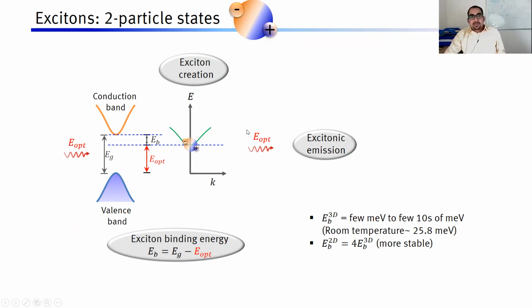Now let's take a look at these binding energies EB. For a 3D exciton, meaning in a 3D material, the binding energies vary from a few meVs to a few tens of meVs. If we compare it with room temperature, which is of the order of 25 meV, then we find that these few meVs would not be very stable at room temperature. So it's very difficult to study these excitons in most semiconductors at room temperature, because the binding energies are small. However, if you create a 2-dimensional exciton, just as in a quantum well, the binding energy is theoretically expected to be 4 times that of the 3D case. So then it becomes more stable and it becomes easier to study 2-dimensional physics at elevated temperatures. So this is one thing we should keep in mind before I move on.